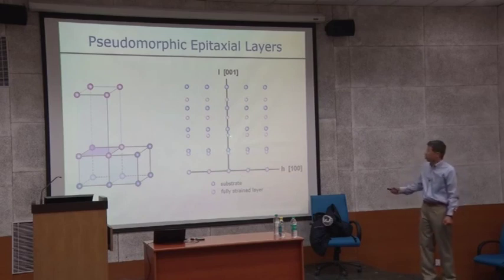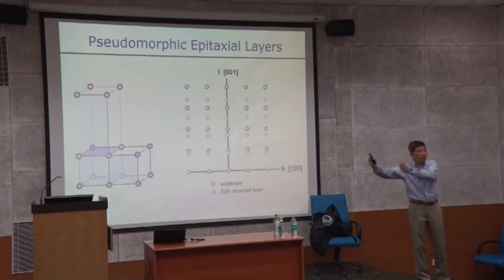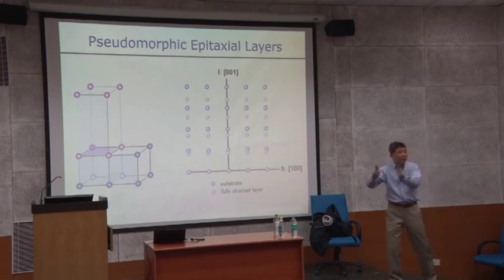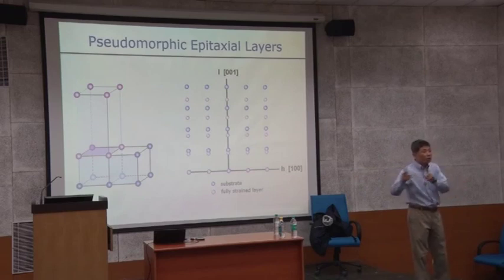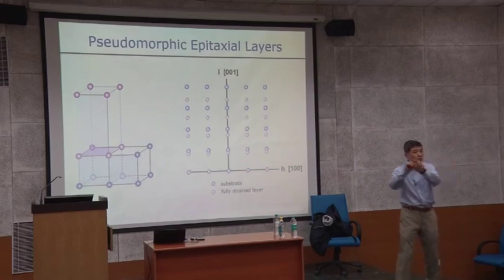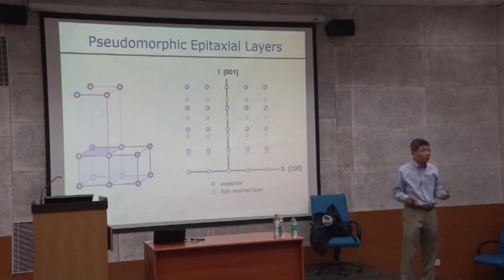And if you scan longer, you get the 001, 002, 003, and the splitting gets bigger and bigger. When you go to higher angle, the splitting gets bigger. That's why sometimes you want to use a higher angle to see the peak splitting. Low angle is closer, and higher angle gives more splitting. This is exactly what a theta 2 theta scan looks like in powder.